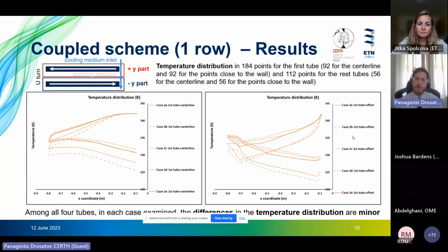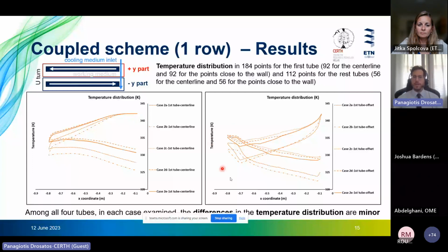The evaluation is again performed by using the temperature distribution both along the center line of the tube and close to the interior surfaces of the metal tube. As you can see, here in the U-turn formation, and close to the wall boundaries, there's a temperature increase of the working medium due to the exhibited zero heat flux or adiabatic boundary conditions, while in the same area and along the tube center line, the trend for gradual temperature decrease is also experienced.